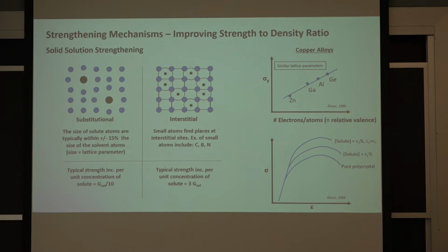If the solute material, if the diameter of that atom, or the lattice spacing, the distance between atoms, is within about 15% of the solvent atoms, then typically those atoms will go to a substitutional position. For example, copper will go, because copper, magnesium, especially magnesium, will go to a lattice position. It's a substitutional alloy. Now, a material that's much smaller, like if you were to add carbon or boron or nitrogen to aluminum, they're so small that they can't take up a lattice position. Instead, they take an interstitial position in between the atoms.